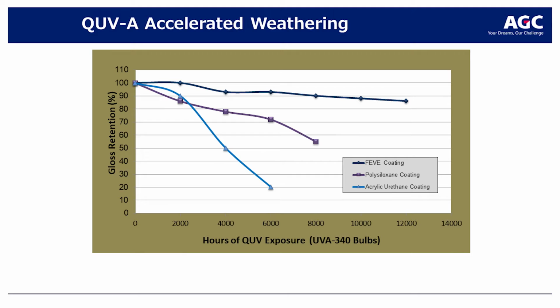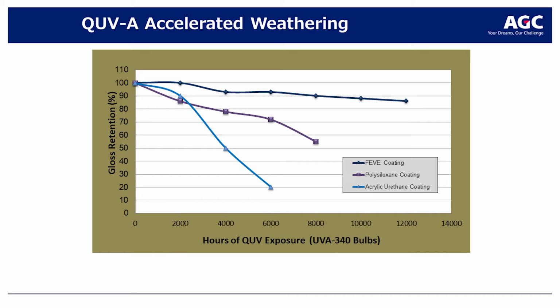When we look at weathering in the coating industry, we look at a couple of different types. We look at accelerated weathering, which is basically exposing coatings to high energies of ultraviolet radiation, and then looking at, in this particular case, gloss retention. The gloss retention is kind of a proxy for the degradation of the coating. So what you want is as small an amount of gloss loss as you can over the life of the coating. And you can see here in this particular case, they've run this out to 5,000 or 6,000 hours. You can see the FEVE coating on the top line.